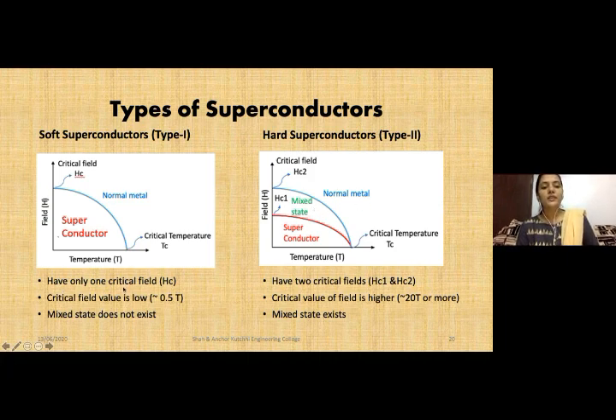So we can see that here we have only one critical field, here we have two critical fields, Hc1 and Hc2, and here the critical field value is 0.5 Tesla. That means the moment you cross around 0.5 Tesla, you lose superconductivity. But if you see Hc2, the threshold at which the material gets converted to a normal material, it is around 20 Tesla. And the last point is, here there is no mixed state, either superconductor or normal material. Here there is a mixed state wherein the material has gradually started losing superconductivity but has not yet become a completely normal material.